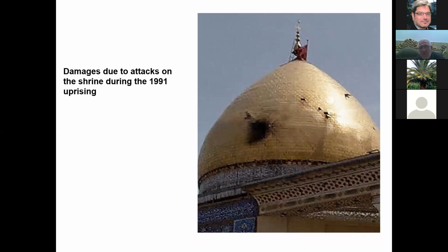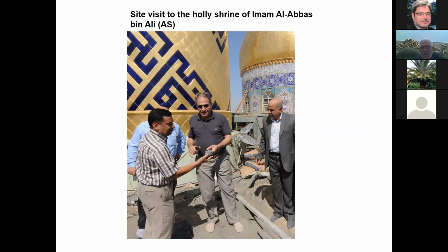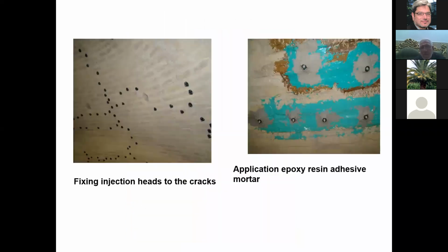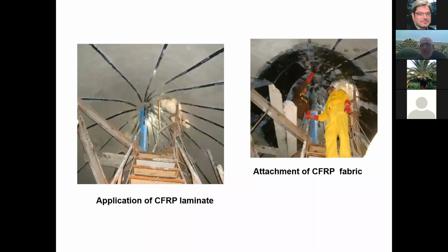Of course, there was also damage to the domes during the uprising of 1991. So we carried out inspections to see what kind of technology was to be used, and eventually what Al-Atabah al-Abbasiyya have done is that they filled all the cracks and all the cavities with epoxy, and then they used carbon fiber composites to strengthen the dome. They removed all the steel skeletons that I showed you that caused damage to the dome, and instead they used FRP. This is the first application in Iraq using an FRP system, and the dome is being monitored, and the system so far has proven to be very efficient and very effective.